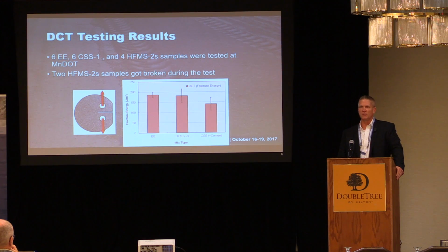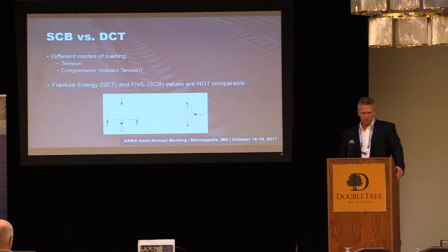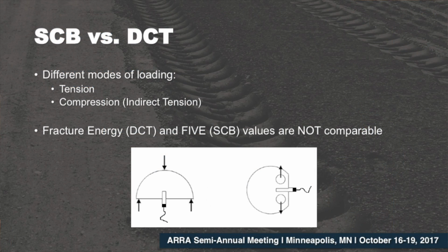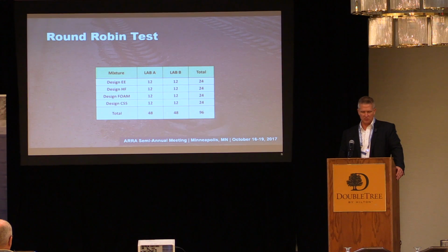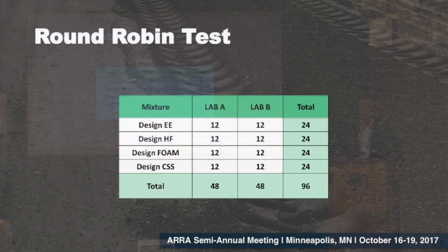And that kind of related back to field performance, in terms of the high float emulsions often showed rutting in the field just because they were really flexible, really soft materials, again, using solvents in the process of making the binder. So those were much more difficult to use in the testing environment, and the feedback from the DOT was negative in terms of their feeling about high float emulsions going forward. So the focus was then more on the other binders, and we looked at the SCB versus the DCT. You look at the different modes of testing, where there's tension and compression, and you want to be able to make sure that the values that you're getting from those test results are going to translate into actual performance of that material in the field.